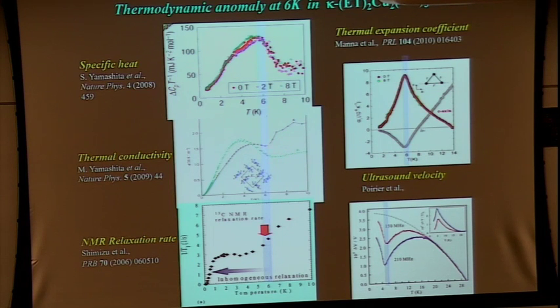However, the magnitude is different, but around 6 Kelvin some kink occurs for both samples. And the nuclear relaxation rate shows a steep decrease around these temperatures. And this is the thermal expansivity, which is also a thermodynamic quantity. This shows some anomalies around 6 Kelvin. And this anomaly seems very sharp. However, in the thermal expansion coefficient, if the transition is of the second order, in that case there is a very sharp peak. So they say this is very broad, the signature of a very broad transition.